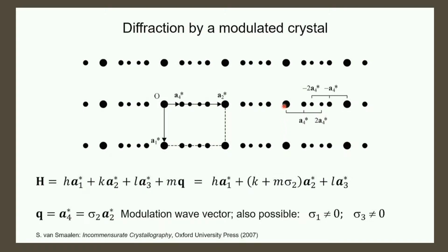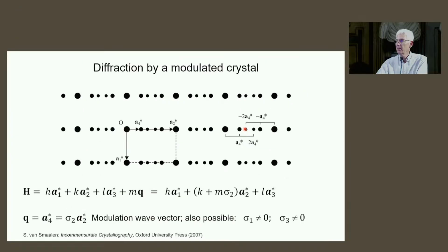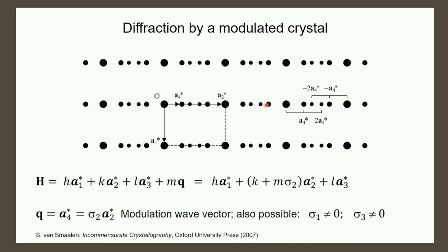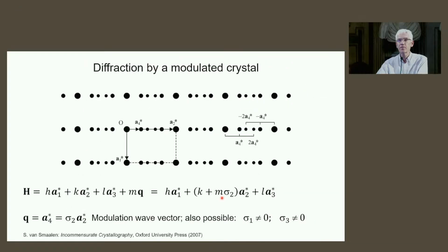And you can see here how easily it gets complicated. A first-order satellite, 1 times q, can be close by a second-order satellite, minus 2 times q, coming from the other main reflection. But if you forget about this indexing and just look here, you see, okay, I have 4 additional spots, how to index them, and it's not always immediately obvious. Another important thing is we index with 4 integers. That is the crucial part. But of course, we can also describe all points in space with 3 indices with respect to A1 star, A2 star, A3 star, except that we have this complicated irrational component of an integer plus this m in front of q times the irrational number of q.